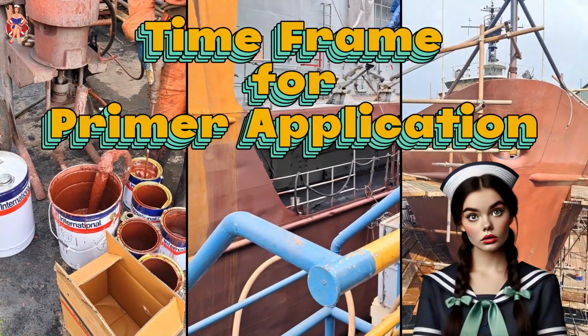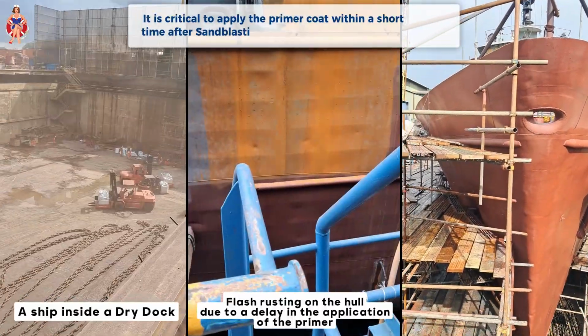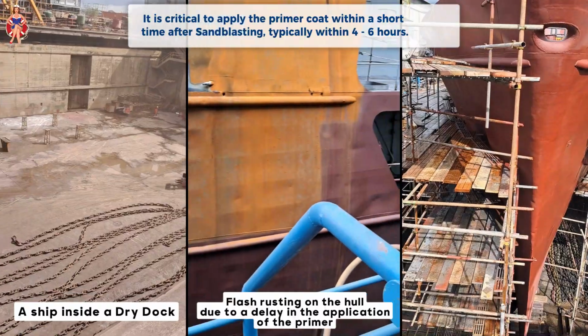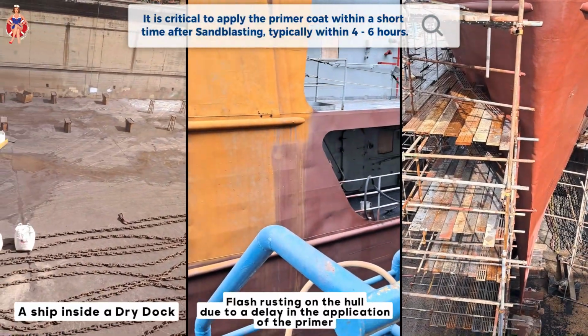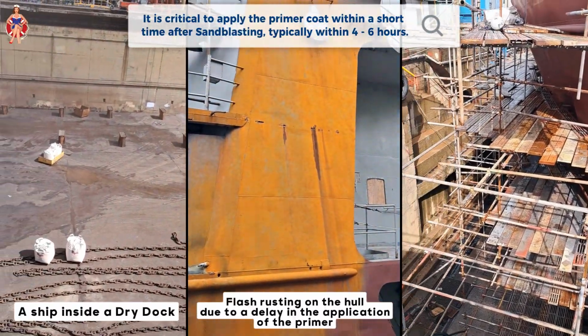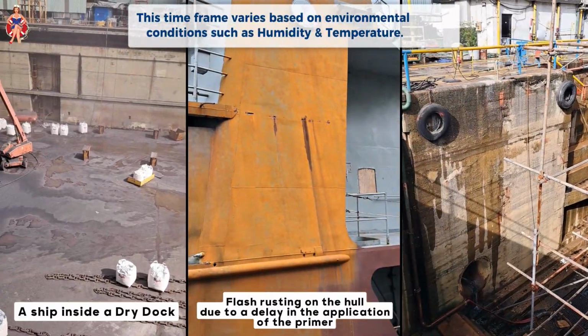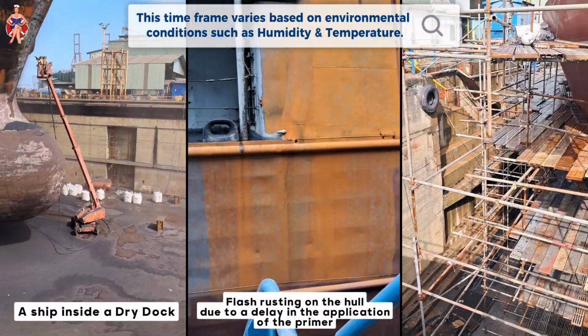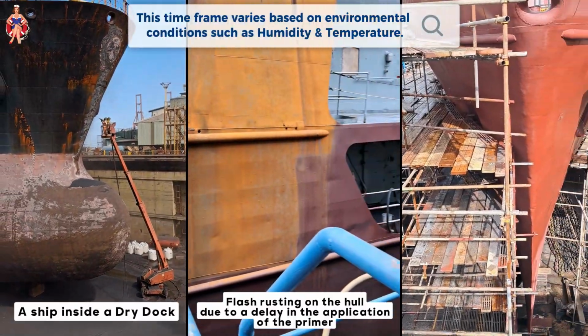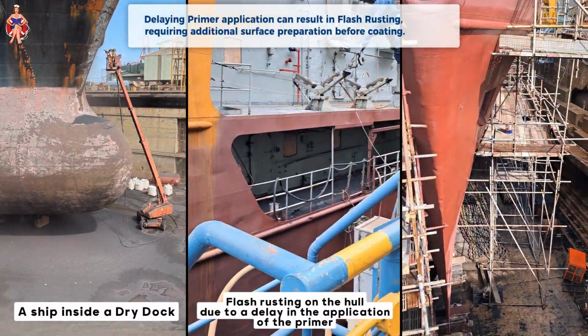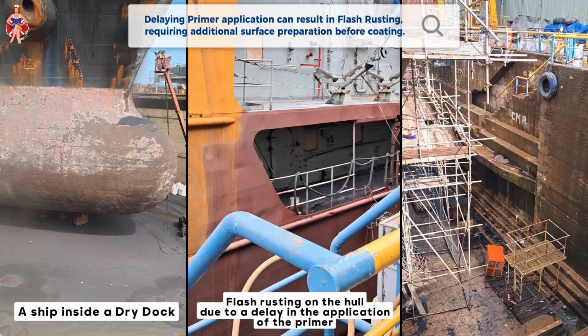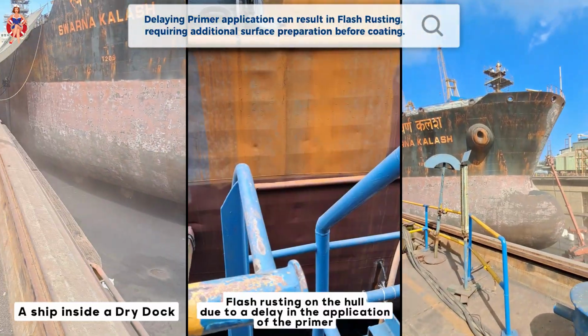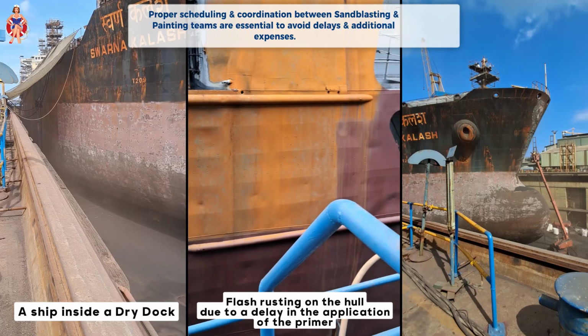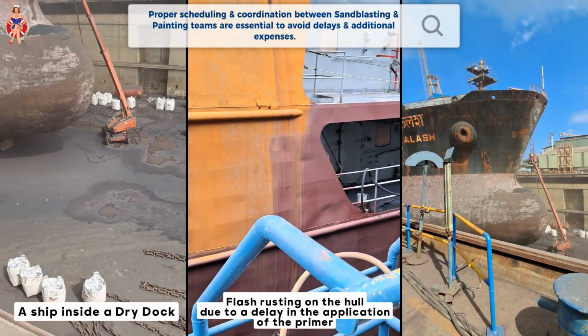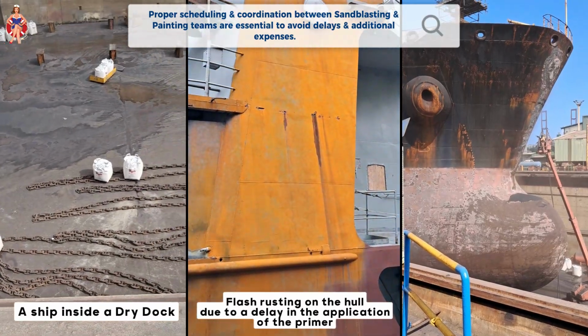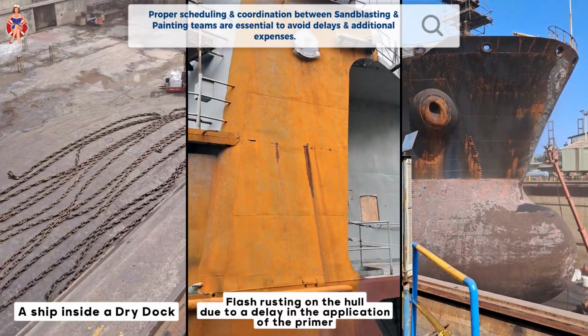Time frame for primer application. It is critical to apply the primer coat within a short time after sandblasting, typically within 4 to 6 hours. This time frame varies based on environmental conditions, such as humidity and temperature. Delaying primer application can result in flash rusting, requiring additional surface preparation before coating. Hence, proper scheduling and coordination between sandblasting and painting teams are essential to avoid delays and additional expenses.